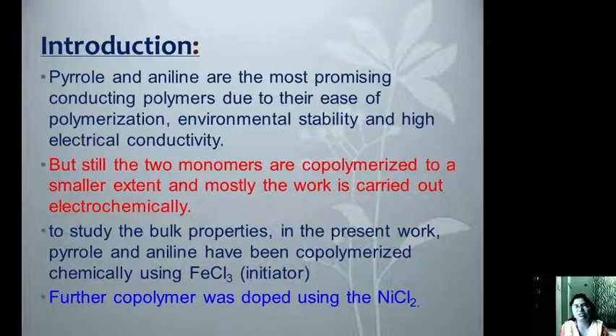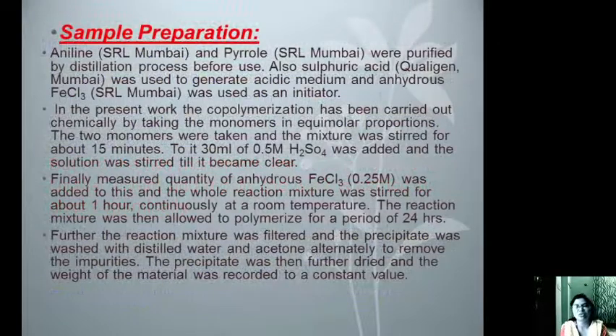But through literature survey, it has been observed that these two monomers are copolymerized via the electrochemical method. In order to study the bulk properties, we have copolymerized them using a chemical method, and the initiator which we have used is FeCl3. For this, I have used pyrrole and aniline in equimolar proportion.